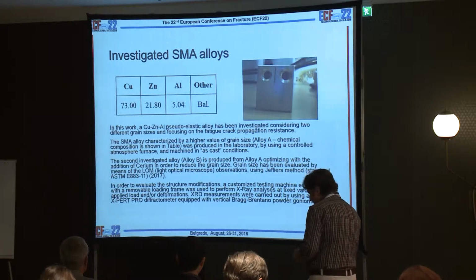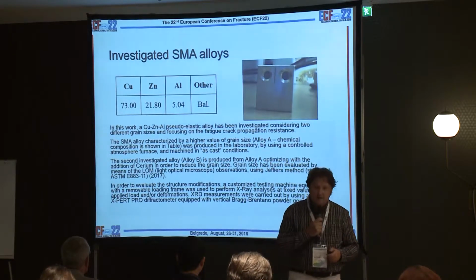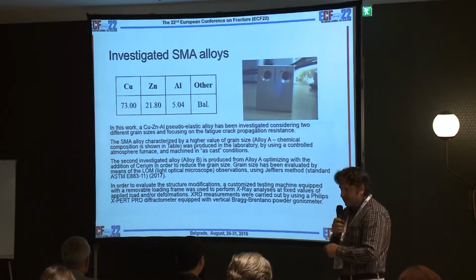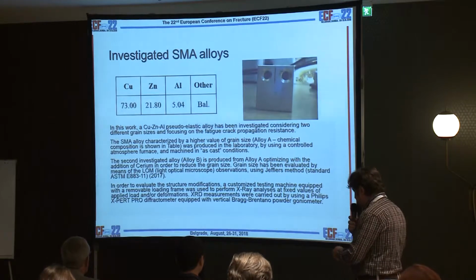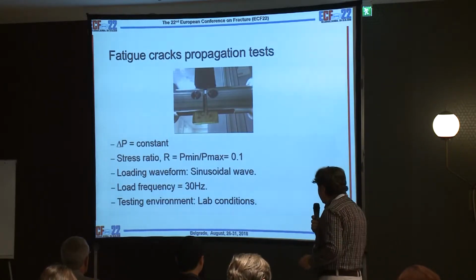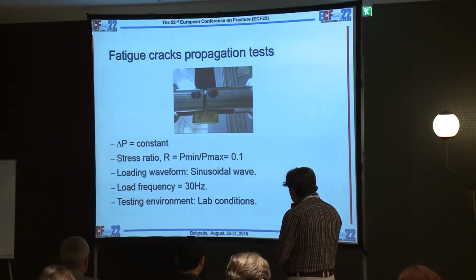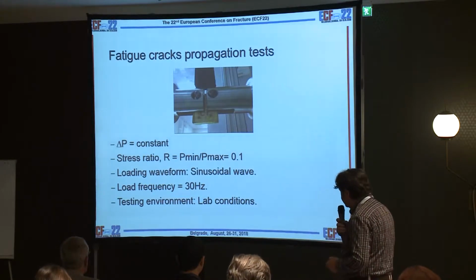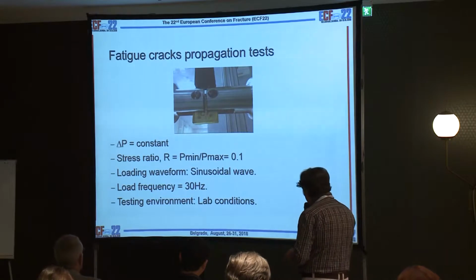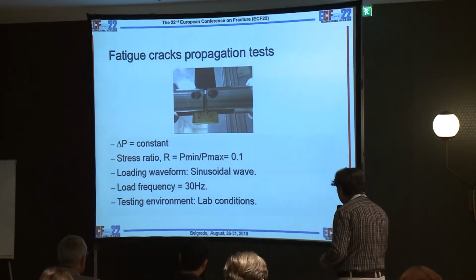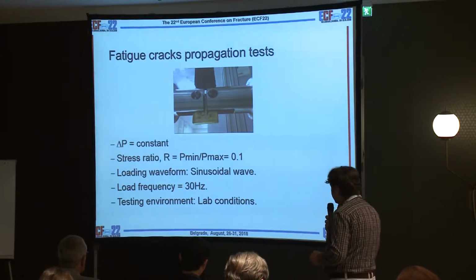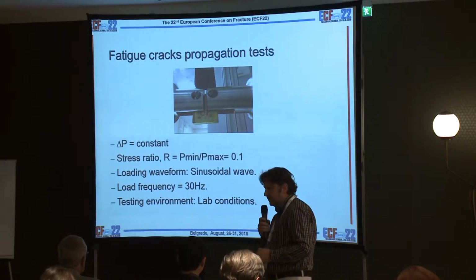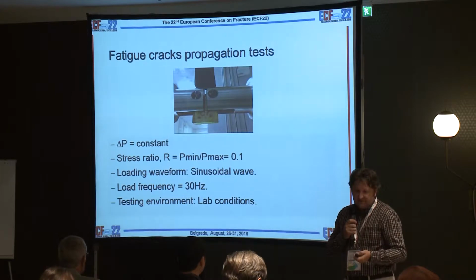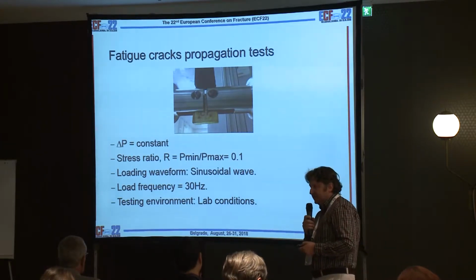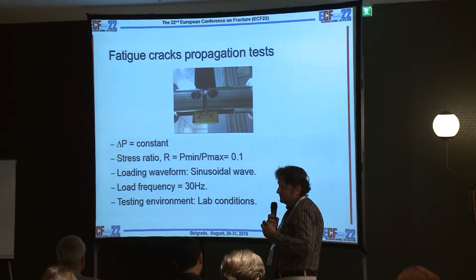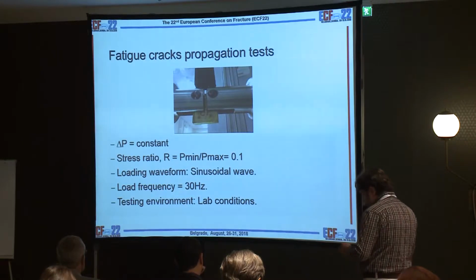Here we summarized the analyses performed on this material in order to evaluate the structure properties and the mechanical tensile properties. Then we performed a fatigue crack propagation test in delta K constant conditions using just one stress ratio R equal to 0.1, with a sinusoidal loading waveform at a frequency of 30 Hz. The temperature was the laboratory temperature, but this material is pseudoelastic. It means that it is not necessary to heat the material in order to have a recovery of the initial shape.